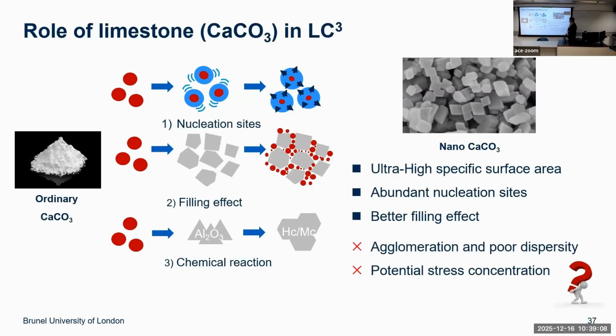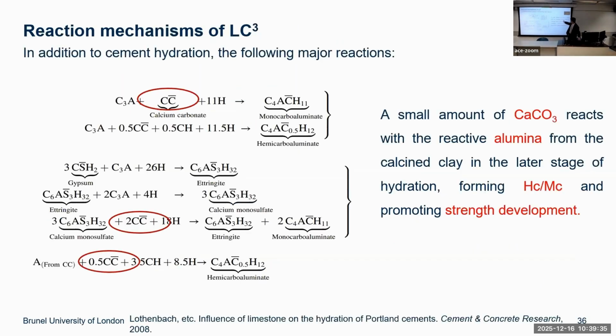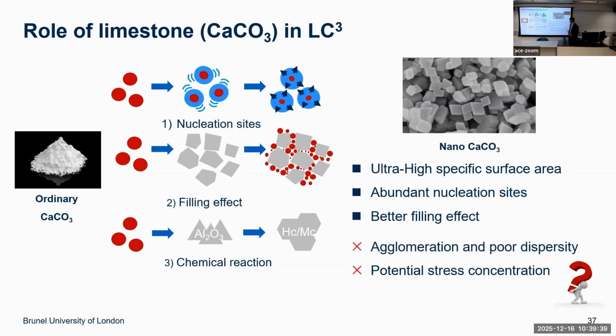Okay, so calcium carbonate, even ordinary calcium carbonate, has three functions. One is to act as nucleation sites, providing a good base for C-S-H, and C-S-H contributes to the strength. Also, because the particles are very small, you have filler effects. And again, it has some reaction: a small amount can react with the aluminate phase. So there are three basic effects. We are trying to generate even smaller calcium carbonate, which we call nano-scale calcium carbonate. They have ultra high specific surface area, provide many more nucleation sites, and because they're smaller, they have much better filler effects.